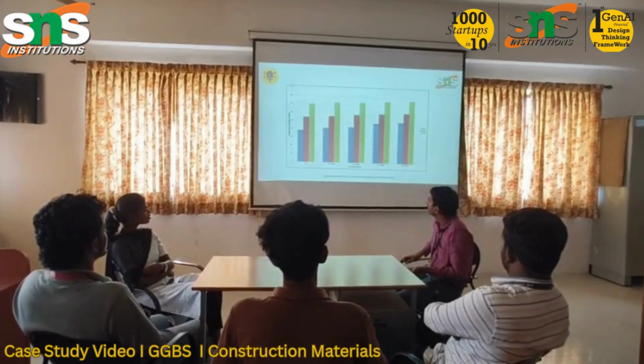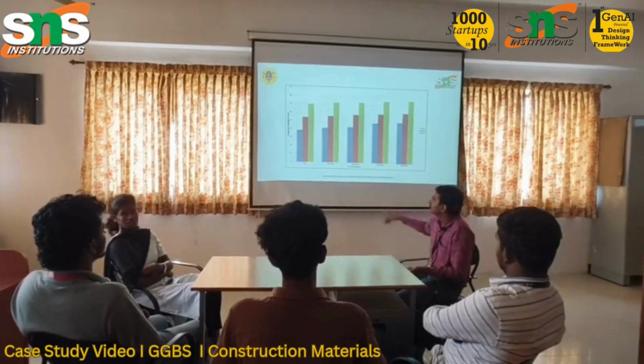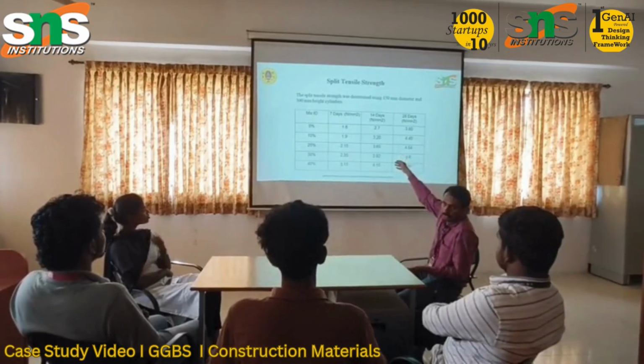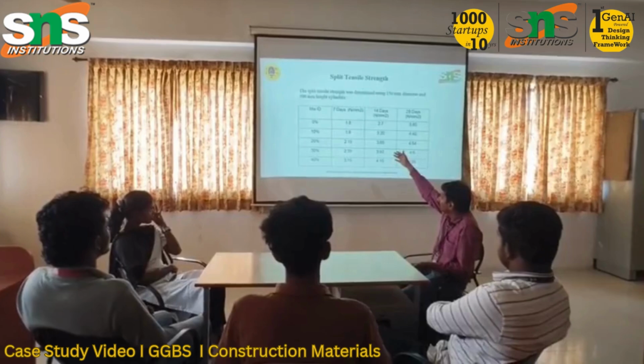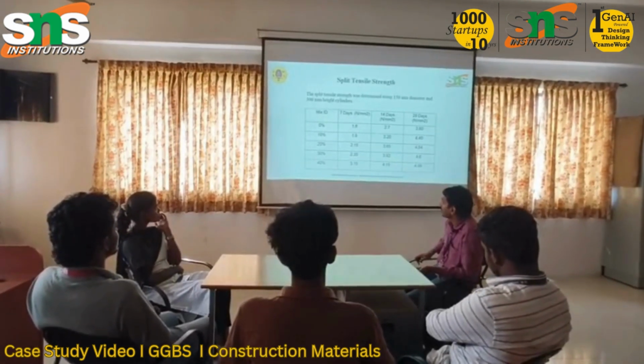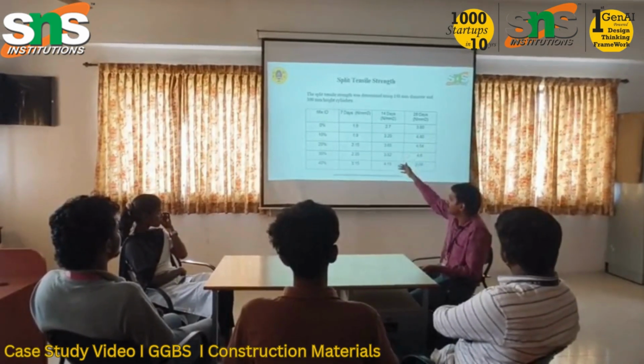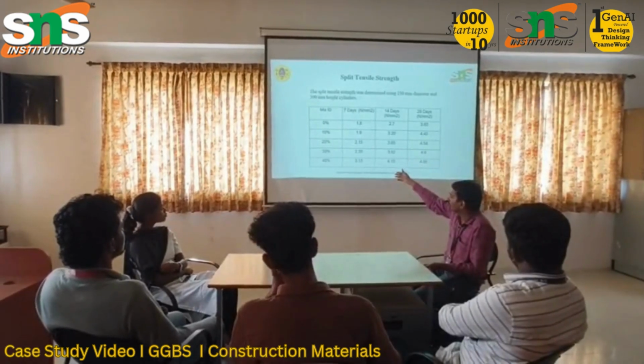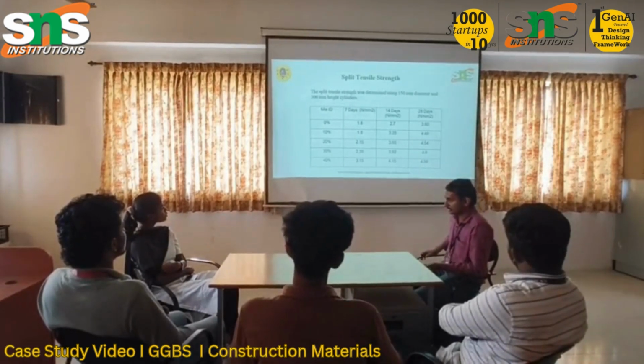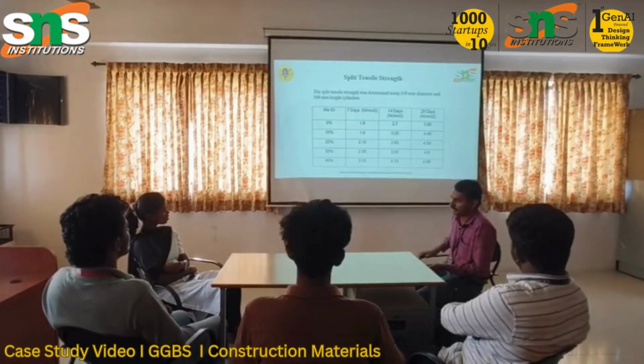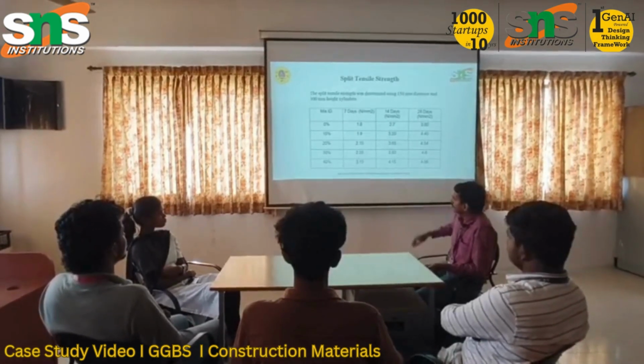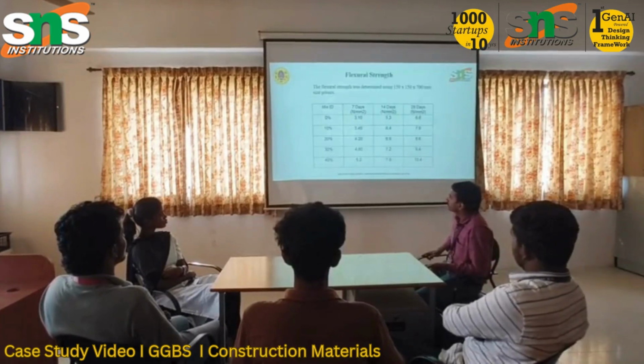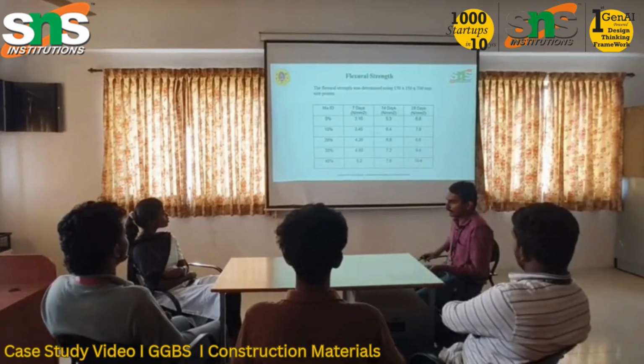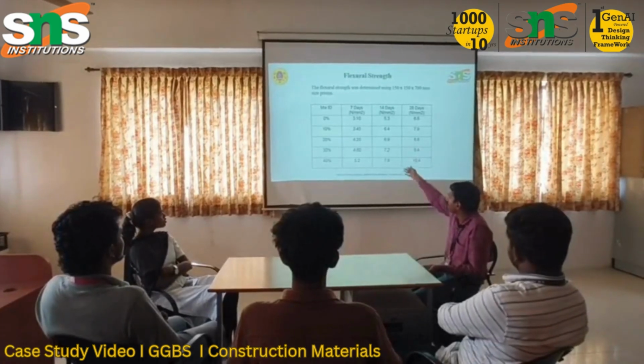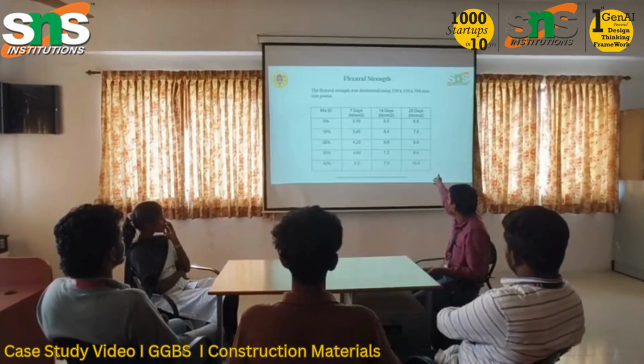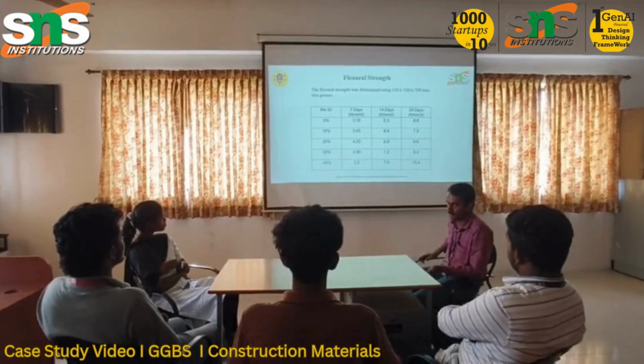The split tensile strength of the concrete has also considerably increased for 40% replacement of GGBS. So the optimized value is 40%. Flexural strength also improved for 40% replacement. We have obtained 10.4 Newton per mm square after 28 days of curing.